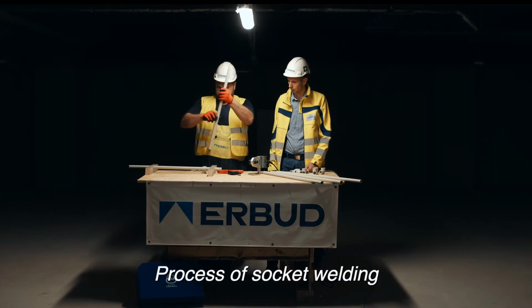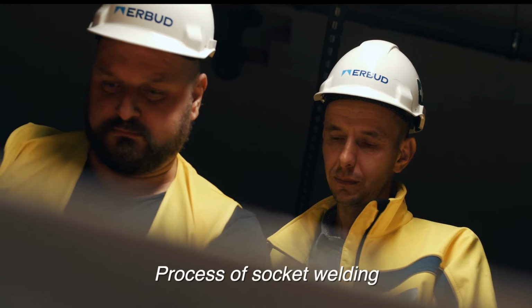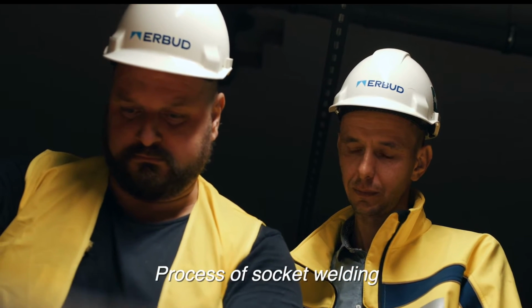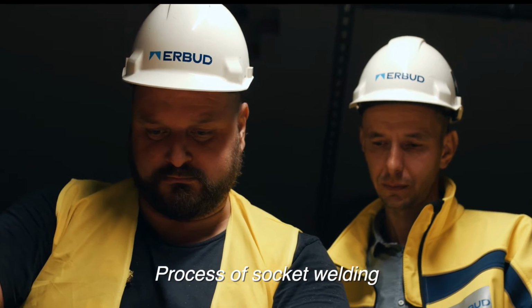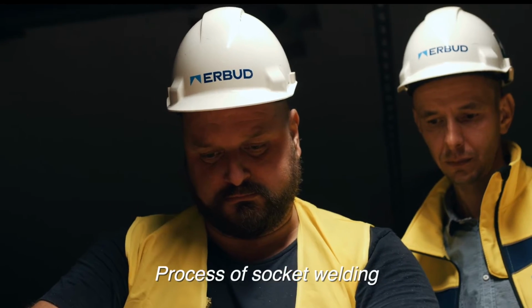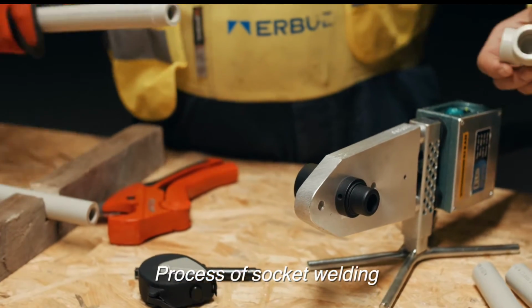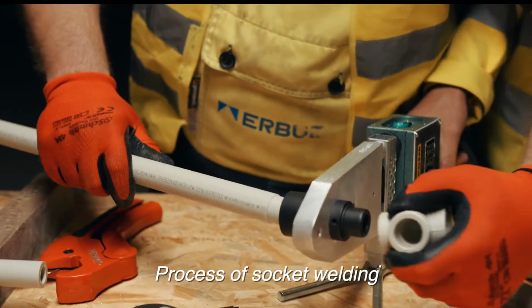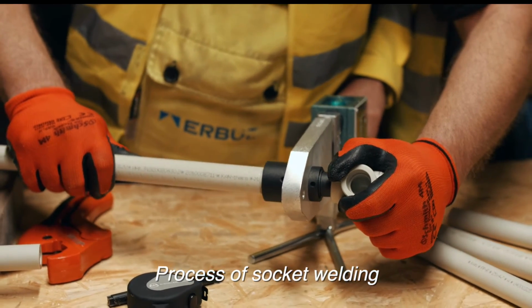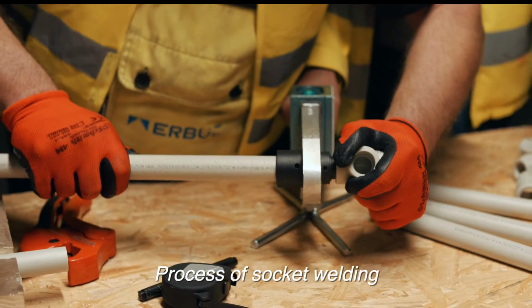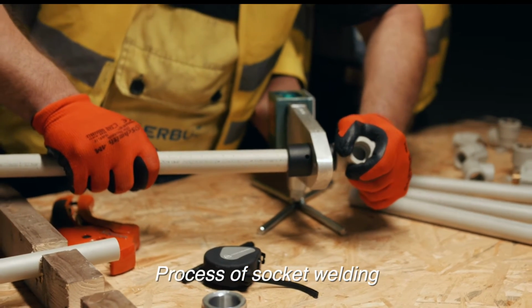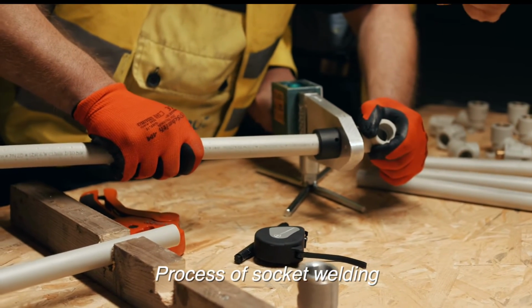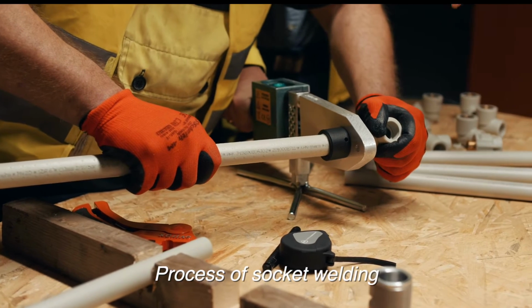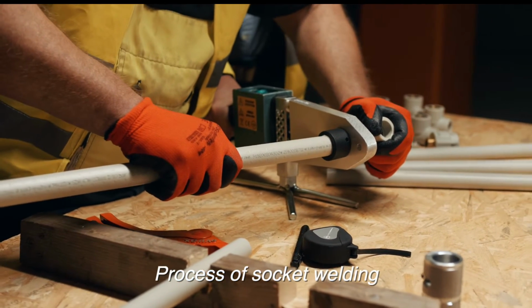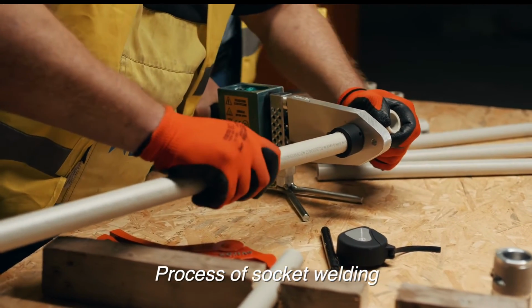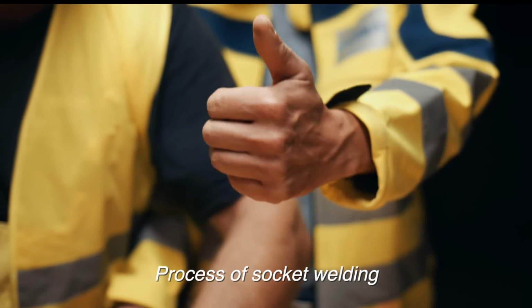For homogeneous pipes and pipes stabilized with glass fiber, mark welding depth manually with a ruler, stencil, or marker pen. The welding area for individual diameters is given in the corresponding manufacturer's instructions. The surfaces to be welded must be clean, degreased, and dry. Insert the end of the pipe without turning it into the heating sleeve up to the designated welding depth. On the other side, also put the fitting without turning it until it stops over the heating spindle. The heating time will count down only when the pipe and fitting enter into the full depth, that is, into the welding depth.